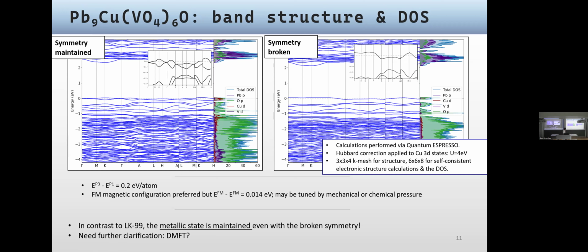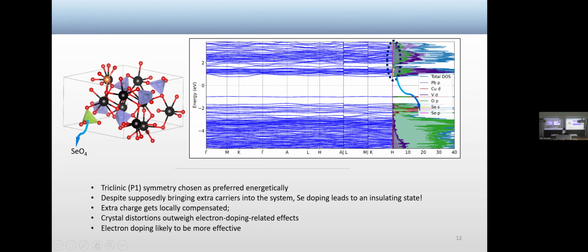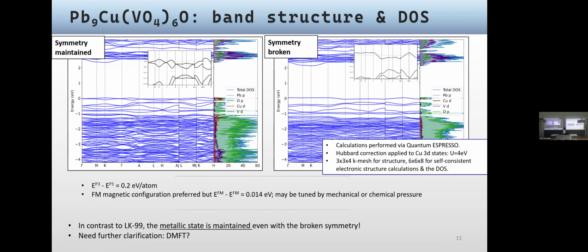And also, the difference between magnetic orderings here becomes very, very small, meaning that in the experiment, it would probably constitute some kind of paramagnetic system. From the point of view of crystal structure, by introducing selenium, we would be replacing those atoms in the tetrahedra. In this way, we completely change the geometry of the copper oxide networks in the system. And this change in geometry is what causes the change in the electronic structure, meaning that the energetic costs of different magnetic orderings change as well. And the opening of the gap at the Fermi level may not be energetically preferred in this case.